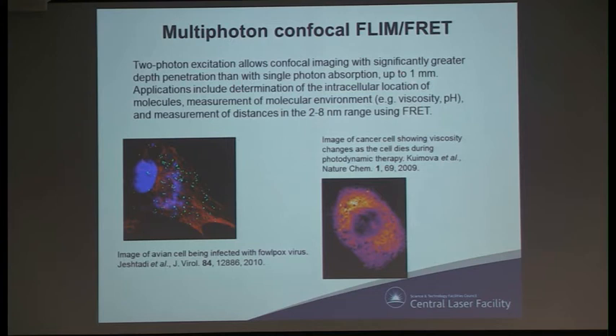So this allows us to go deeper into the samples. This here is an example of that - this is basically an avian cell, which is the red and blue areas, and the green is a fowlpox virus within that. So we go much deeper into the cell to get much better depth imaging, and we can also start to map more of the molecular environment.